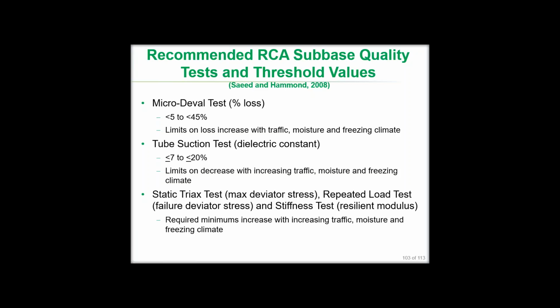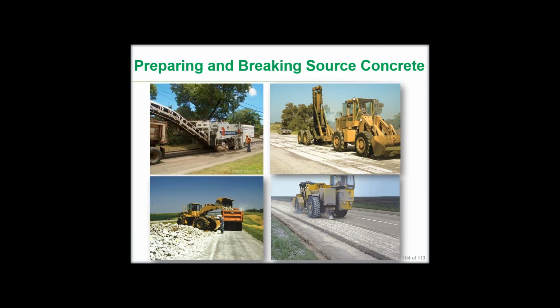The threshold values for these tests varied depending upon the traffic level that was going to be used on the pavement on top of it, the environmental conditions, the moisture conditions, and the general climate, whether it's a freezing climate or not. With those things in mind, you could have relatively low quality materials that might not be suitable for a high volume, high type application, but this identified lower level applications where they might be used. So this all goes back to the concept of using materials in their highest possible application for the most effective recycling.